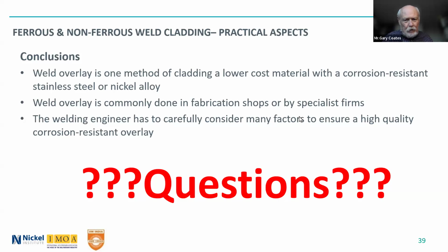How can we achieve E410 weld metal chemistry to meet 410 clad and base metal, 5/16, 60 or 70, required height of weld overlay, I guess, is the 6 millimeter. That is tough. I'd have to think about how to do that. I mean, welding 410, I presume it's a 410 where you're not looking for a high hardness. You're just looking for a 11-12% chromium content in the overlay there.